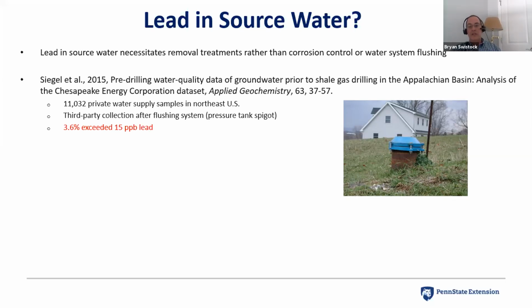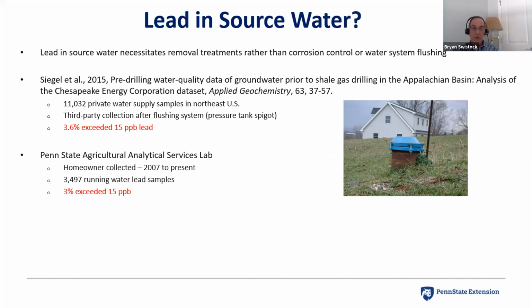Now, there have been some studies here in Pennsylvania that have looked at source water contamination from lead. There was a large look at pre-gas drilling samples in large areas of the state. Over 11,000 samples were collected, and these were basically pre-treatment samples, so they would be ideally coming from the well itself, and they found 3.6% of those samples had more than 15 parts per billion of lead. So that's a pretty significant number. That indicates a more significant source water problem with lead than I would have maybe expected.